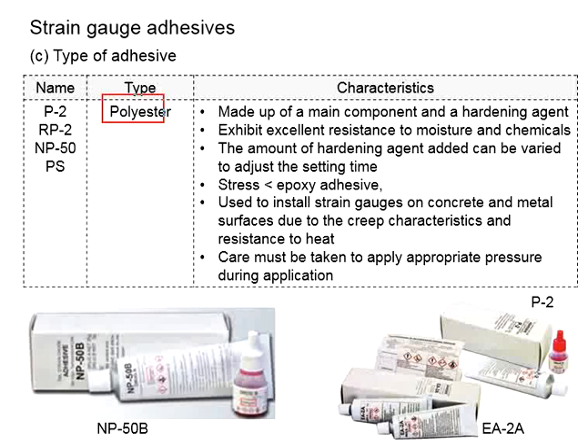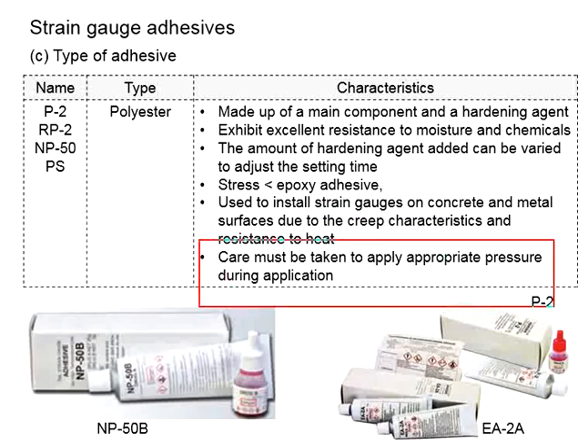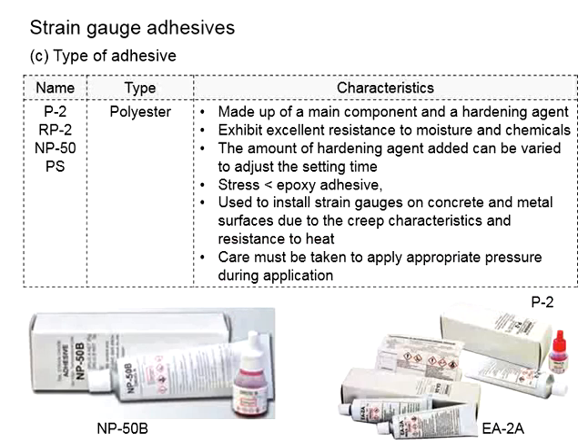The second type is the polyester. It is made up of the main component and the hardening agent. It exhibits excellent resistance to moisture and chemical. Now the amount of hardening agent is added based on the intended setting time. You may adjust the hardening agent for different setting times. The stress now is less than epoxy adhesive, and it is normally used to install strain gauges on concrete and metal surface due to the creep characteristic and resistance to heat. Care must be taken to apply appropriate pressure during the application.